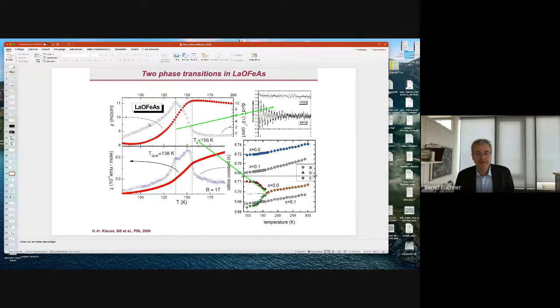So this is, again, very early data from a very early work. So we have this lanthanum oxygen iron arsenide, this parent compound. We cool it down, and then there are 2 phase transitions. You see here, for example, in the susceptibility, these 2 peaks. And the second one is indeed the magnetic phase transition. So muons then show a rotation. This is a spin density wave. And before we go into the spin density wave, we do a phase transition from a tetragonal to an orthorhombic state. So we break C4 symmetry at that point. And this is, in some sense, the signature, the reason why we discuss nematics. That's the reason why I believe orbitals play a role.